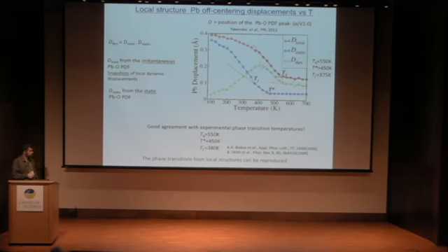Okay, so the first thing, this was from 2013, we looked at the local order parameter for relaxor phase transitions, and we took something very simple, which is the displacement magnitude of the lead in PMN-PT. This is the total displacement magnitude, and you can see that in the high temperature paraelectric phase it rises very slowly. At the Burns temperature around 550, the rise becomes sharper, and then it kind of plateaus right over here at the freezing temperature.